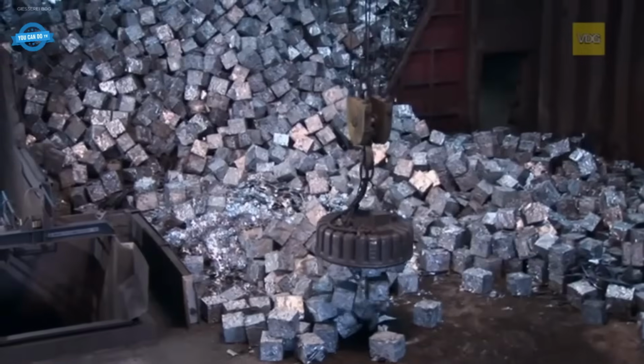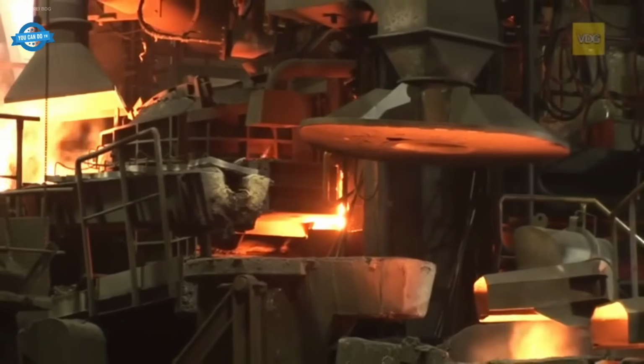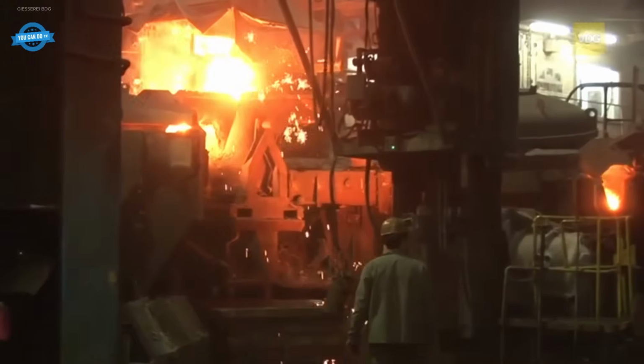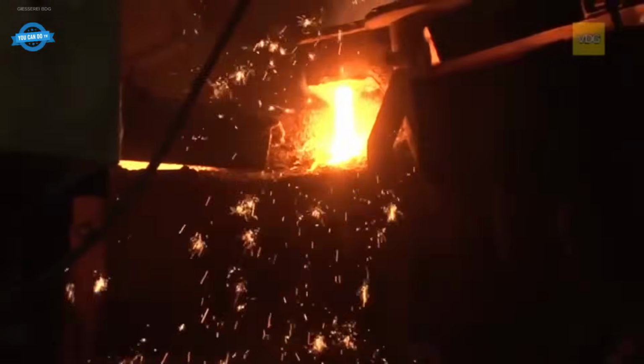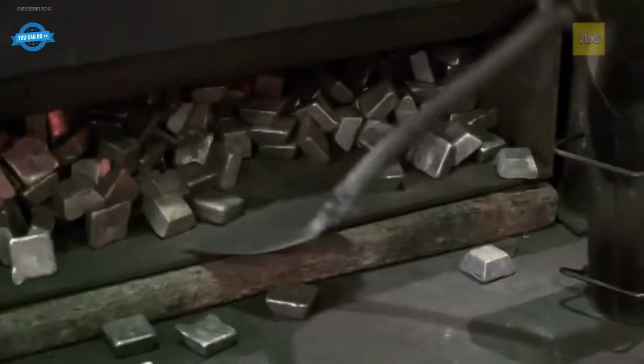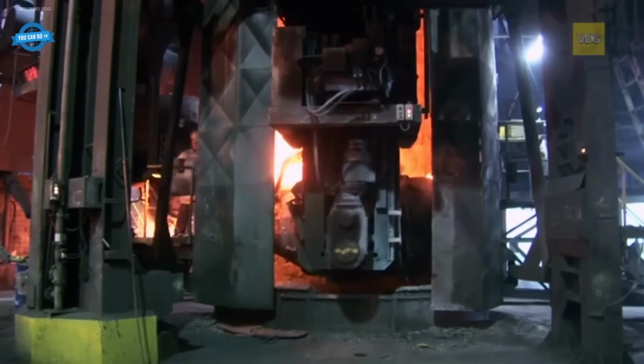Advanced manufacturing includes hybrid casting techniques. The insert is first coated and preheated, then placed in the die cavity. The magnesium is injected at speeds of 30 to 90 meters per second, under pressures up to 1,200 bars, creating metallurgical bonds between dissimilar metals. This enables lightweight crankcases for automotive engines.